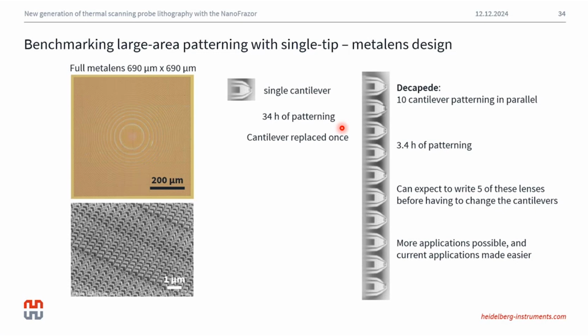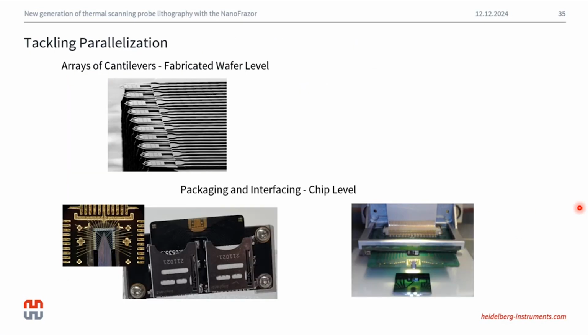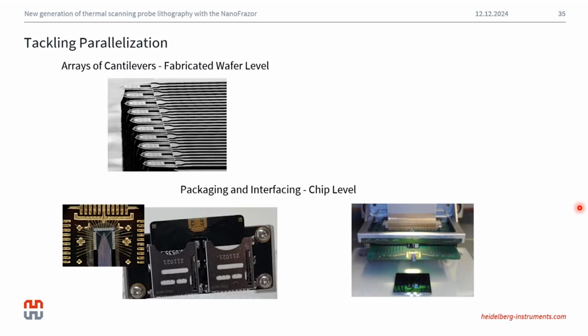And with the decapede, we can use 10 cantilevers to pattern features in parallel, and this would reduce the patterning time of a metal lens down to 3.4 hours of patterning, for example. And if we can expect the same type of endurance from the decapede as well, then you can expect to write 5 of these metal lens designs before you need to change the cantilevers. Using such a multi-tip module allows us to expand our application space and renders our current applications much faster and much easier. And this is how we're tackling parallelization with the new NanoFrazor.